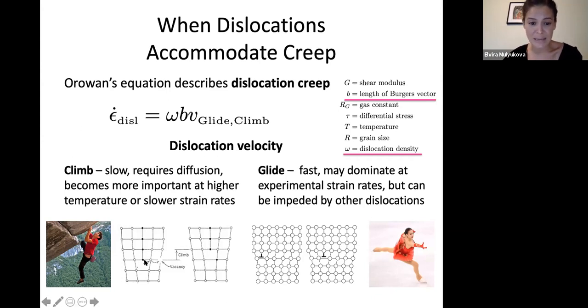So this is climb, which is schematically shown here. If you're thinking of a dislocation as just kind of a plane of atoms or plane of vacancies shoved into a crystal, climb would just be kind of transferring vacancies to and from that plane in order to have it move out of its slip plane. Okay, and then we have glide, and glide is typically a lot faster, mainly because it does not require any sort of diffusion of material across your crystal. Just kind of this typical, here shown for the example of an edge, just hops over these potential wells as it moves along in its glide plane.